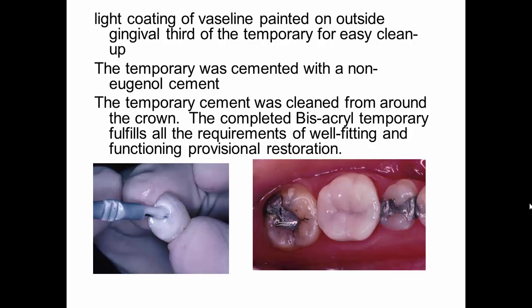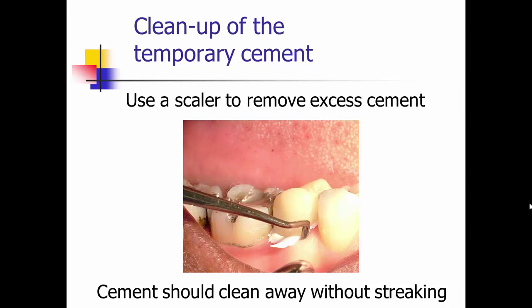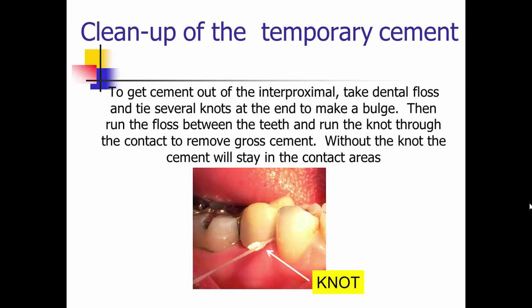Once the temporary cement is set, I clean it up from around the tooth. I typically go in with a scaler. I don't use an explorer. In fact, when you wait till the cement is set completely, it'll clean up without streaking. For the interproximal cement, I'm going in with a piece of dental floss that I've tied into several knots. I floss between the temporary crown, pull it out, the knot pulls out the excess. Without those knots, the floss is just going to go between the cement and the temporary crown. It won't remove that excess cement. Leaving the excess cement will lead to gingival inflammation. You'll get bleeding when it comes time to cement the final restoration.